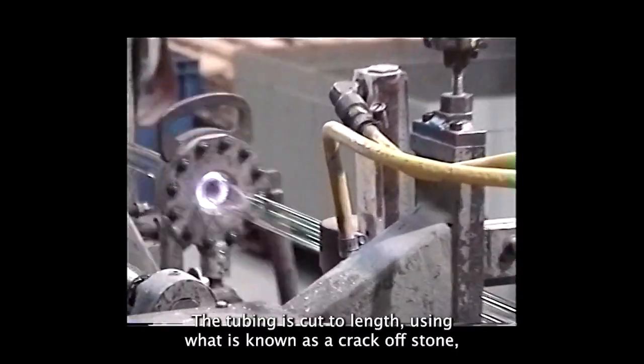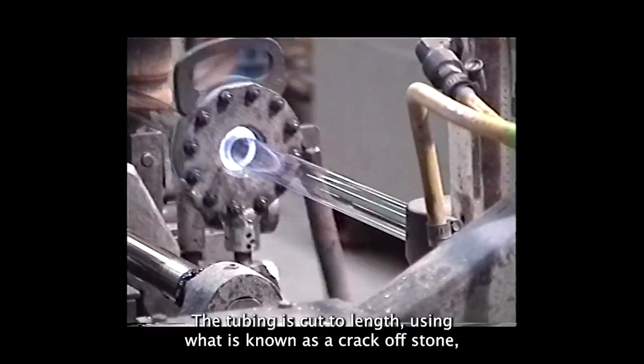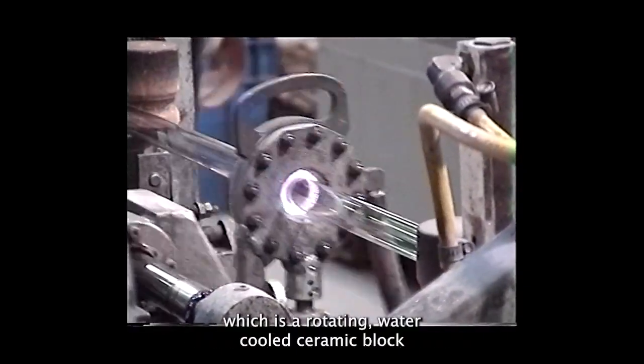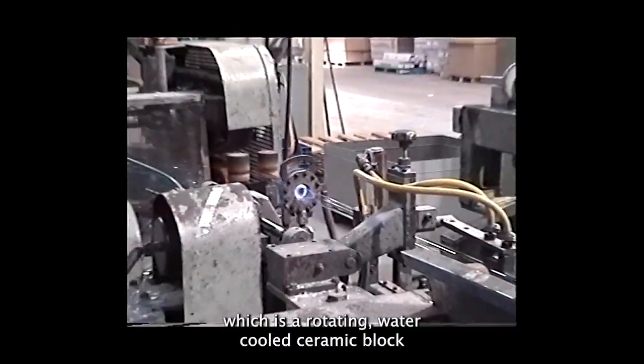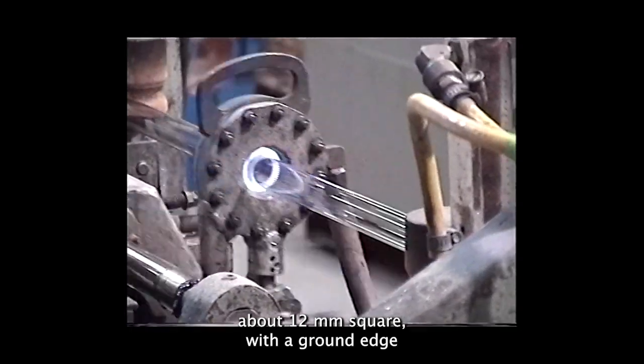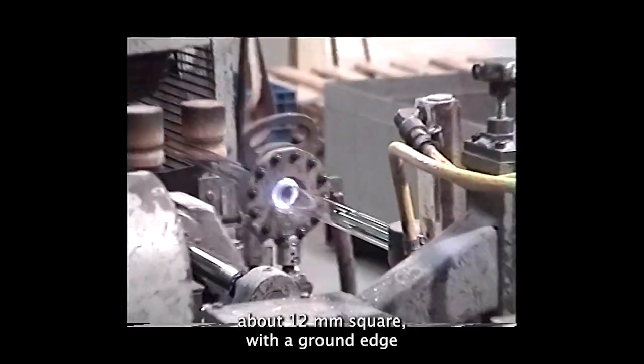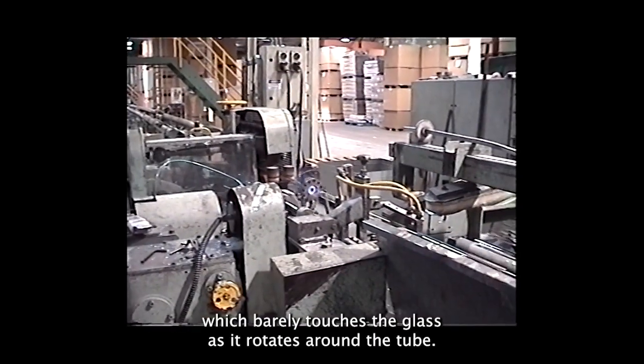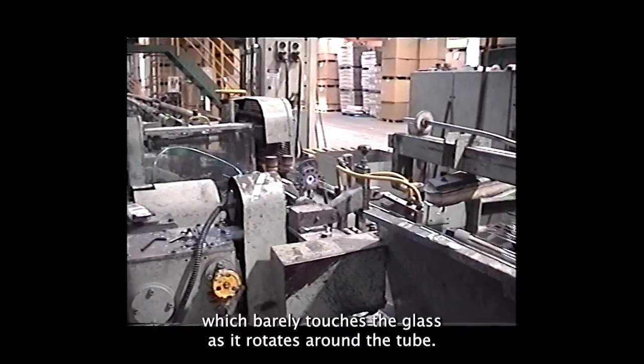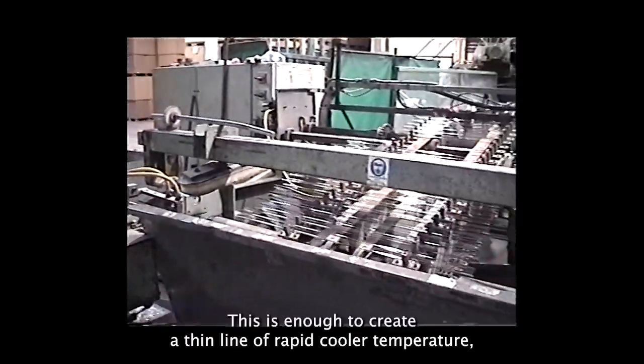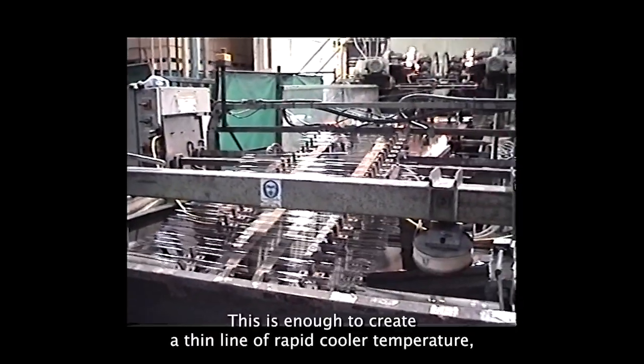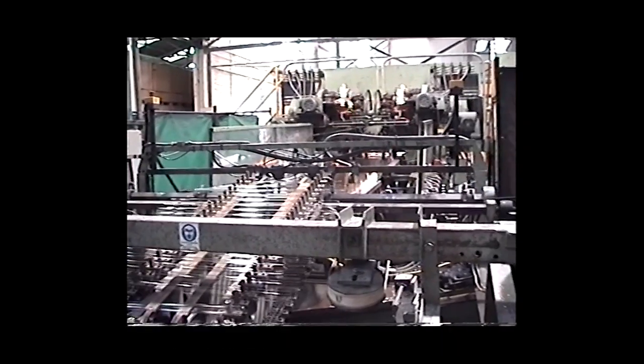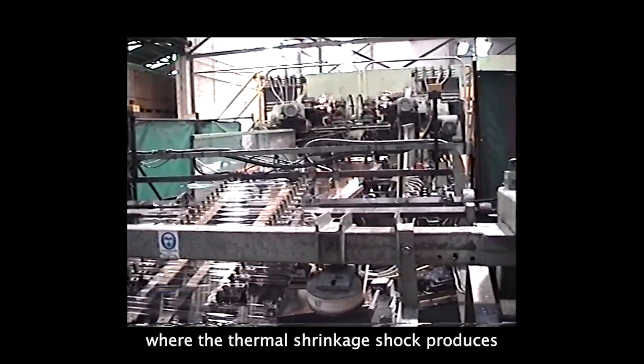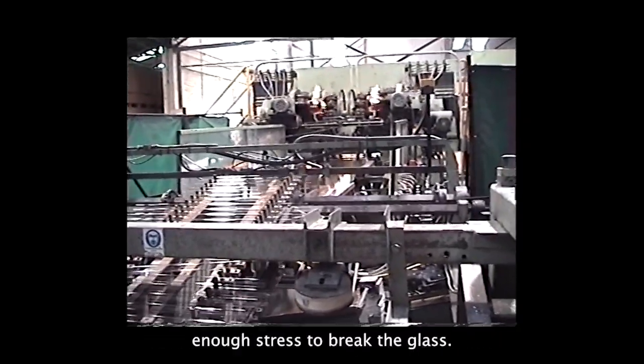Tubing is cut to length using what is known as a crack-off stone, which is a rotating, water-cooled ceramic block, about 12 millimetres square, with a ground edge which barely touches the glass as it rotates around the tube. This is enough to create a thin line of rapid cooler temperature, where the thermal shrinkage shock produces enough stress to break the glass.